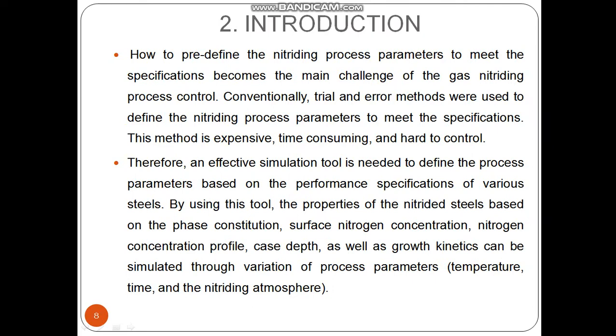By using this tool, the properties of the nitrided steel, based on the phase constitution, surface nitrogen concentration, profile, case depth, as well as growth kinetics, can be simulated through variation of process parameters: temperature, time, and nitriding atmosphere.